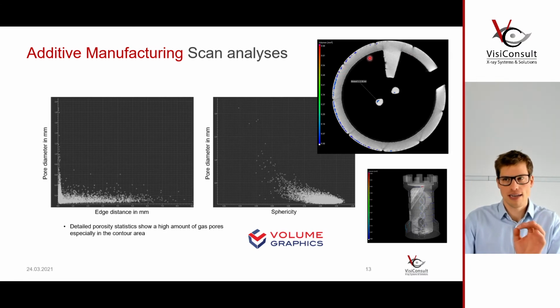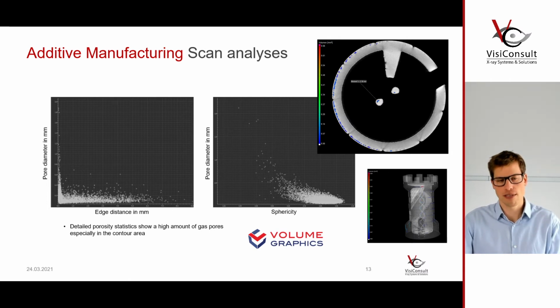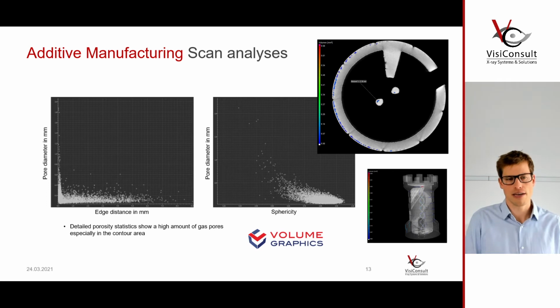And in many cases, small porosities are not a big deal. You can have them. These small porosities probably will not impact the part integrity. But if you then surface treat it, you have them open, it does not look nice. It might have adverse effects with lubricants and stuff like that. So you have to be very mindful on how you surface treat your parts, how thick you create this outer hull. And this is all insights that you have to already have during the manufacturing phase, which you can only